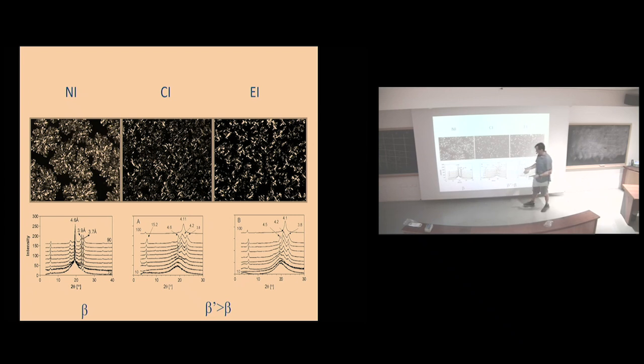Now, you hit it with the catalyst, and all of a sudden you get, except for the 100% one, which obviously is not transformed, look at that, 3.8, 4.2, and a little bit of the 4.6. If you read those tables, you'd say that's beta prime now. So by interesterifying, I made beta prime. This is how interesterification came to be in the 50s when they started interesterifying lard to make better pie crusts, make them more plastic, make them more smooth. You need a beta prime.